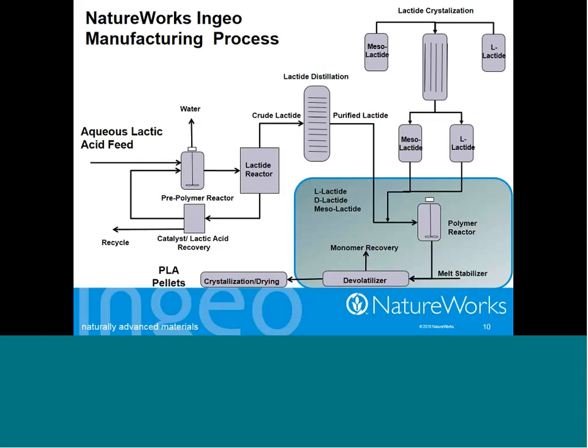So if you think about a process being run at, let's say, 180 degrees, you could consume up to, or have an equilibrium lactide concentration at the end of the polymerization of about 3.5%. If you increase the temperature, the amount of equilibrium lactide present at the end goes up a little bit, so it would maybe go to 5%. The other thing I'll mention is that this is all done in the melt. The reaction mass needs to remain above the melting point of the polymer that we're making so that it doesn't crystallize out on the inside of the reactor as it's being made.